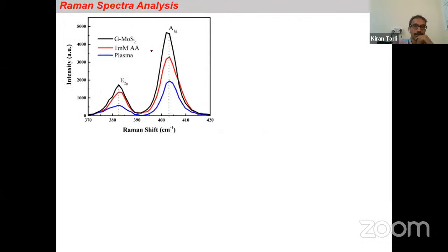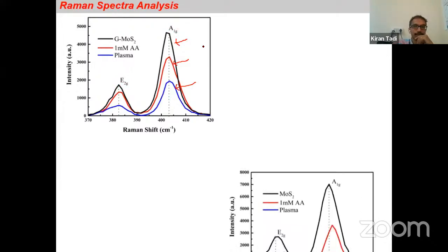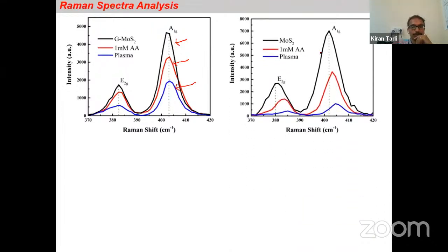You can also see the Raman spectra of graphene-MoS2. This is simple graphene-MoS2, and this is after interacting with ascorbic acid and after etching the surface with plasma. There is no shift in the E2G and A1G, the characteristic peaks of the Raman spectra. Whereas in the case of simple molybdenum sulfide, under the same conditions, there is a shift in the peaks.